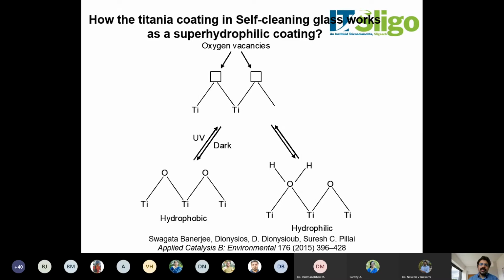And once the oxygen vacancies are created, the water can easily fit into these oxygen vacancies, because water has lone pair of electrons. That is how the titanium dioxide will be acting as a hydrophilic or water loving surface. So this is how a hydrophobic surface will be changed to a hydrophilic surface. We have published an extensive review on this in 2015. My colleague, one of the senior researchers from Trinity College, Swagata Banerjee, mainly wrote this review, and it is available online. It's published in Applied Catalysis B, 2015.